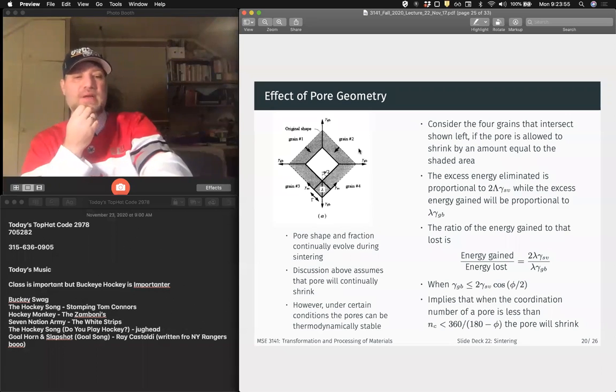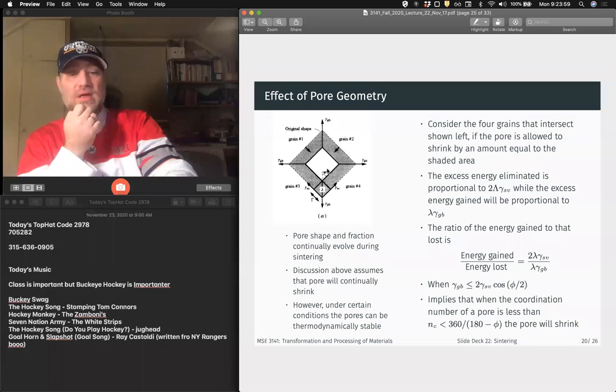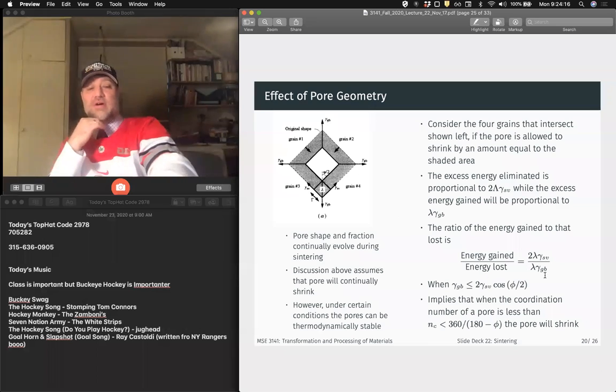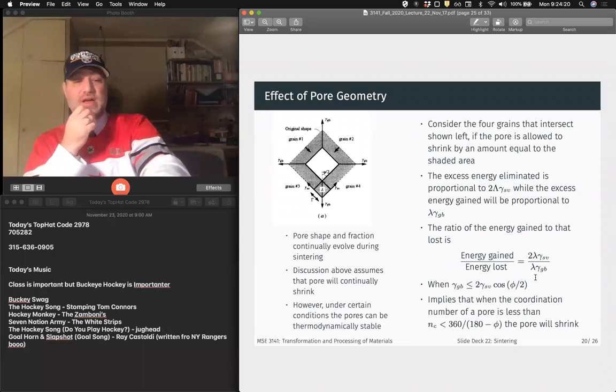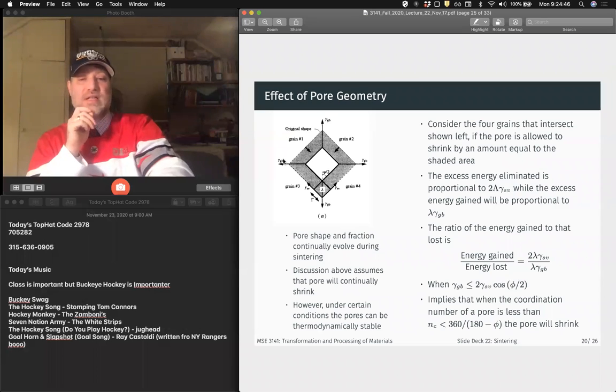Okay. So what is the energy eliminated, right? So we can do our geometry and figure out how much of this solid vapor interface we're eliminating versus how much grain boundary area we're eliminating, right? And we end up with a ratio that looks like this, right? And so essentially, if we have a balance between the grain boundary energy and the solid vapor surface energy that is of this form, right, where our grain boundary energy is less than 2 times our solid vapor surface energy times the cosine of the contact angle here, then this pore is going to shrink.